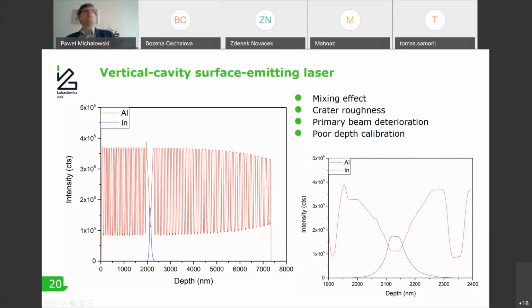So I will not maybe explain in detail everything about the procedure that I made, but I'll mention that I made an additional, very enhanced procedure where I was also polishing the crater from time to time, to decrease the roughness, used a very low impact energy and high incident angle to decrease the mixing effect. And when I was also polishing the sample, just a little bit, I was also making sure that the primary beam condition stays in shape.